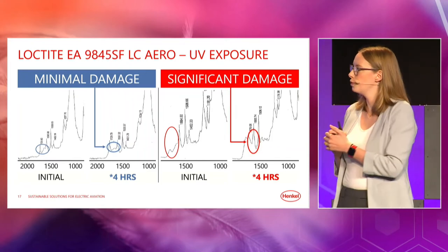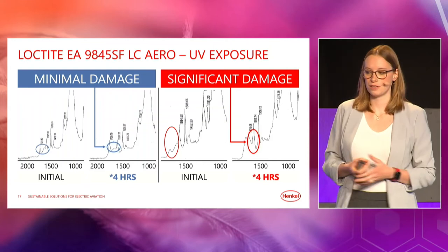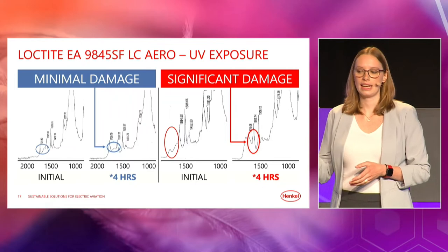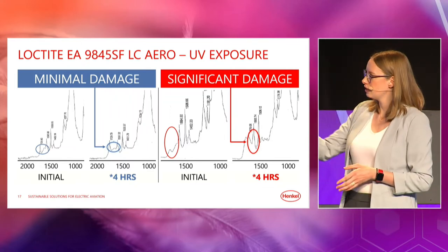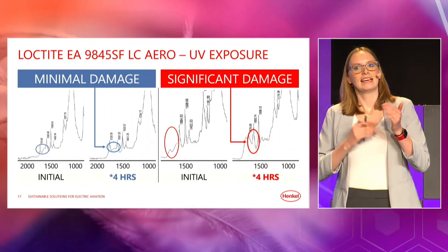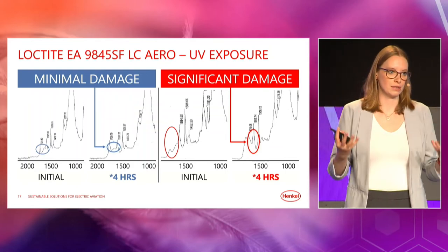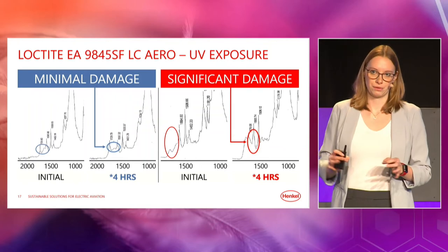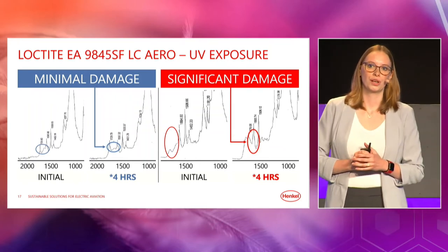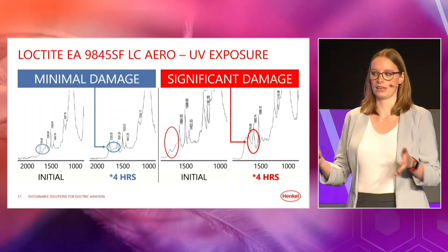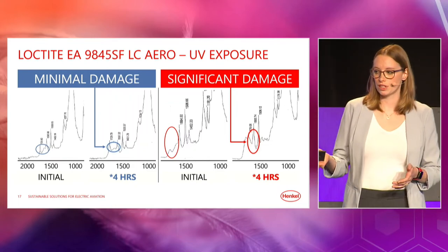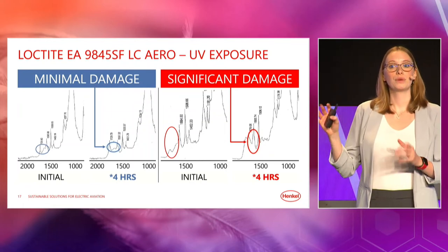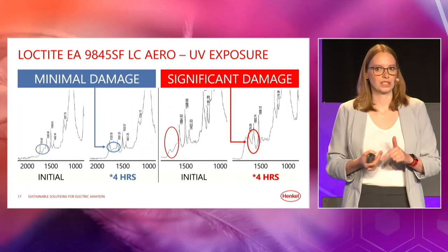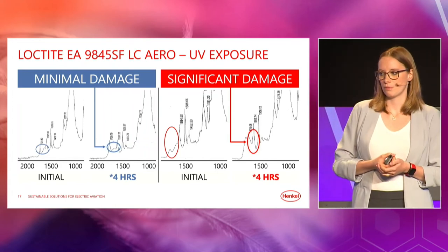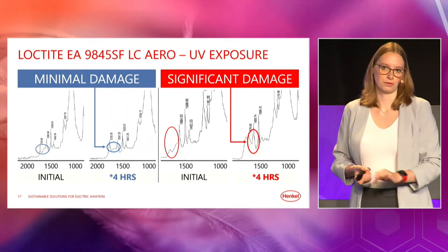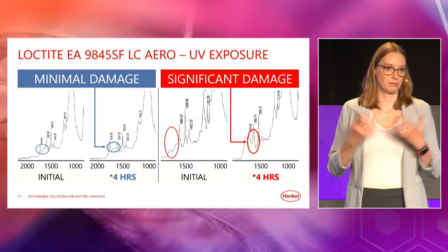And what we've done, I hope you can see the graphs properly, is FTIR measurements. And on the left side, the blue graphs, this is our 9845 surfacing film. And we have measured the FTIR initially and after 4 hours of UV exposure. And you can see in the blue circle, at this specific wavelength, it changed minimally, and therefore we have minimal damage in the material, but it looks very, very good. On the right side, however, we have tested a non-UV-resistant surfacing film, and again, initially FTIR measured, and after 4 hours of UV exposure, you see a significant damage. So on the right side, we cannot be sure that the mechanical characteristics or corrosion protection is still there as the initial product was designed. But on the left side, with the 9845 surfacing film, we can be sure that those properties are still there.